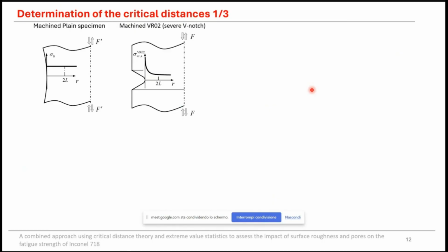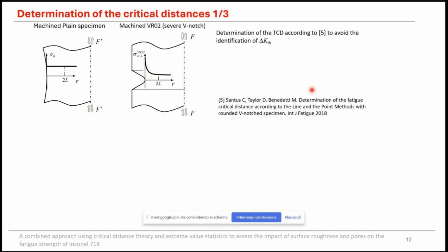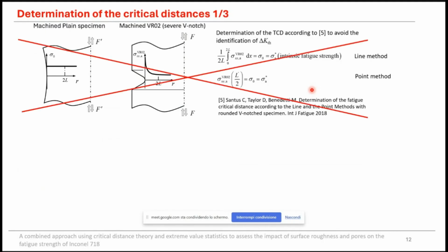In principle, we wanted to use a combination between the plain machined specimen and the severe V-notch machined specimen, following the approach proposed by Santus, Taylor, and Benedetti to avoid the identification of the threshold stress intensity factor range, which can be challenging to identify experimentally. However, this approach could not be applied, given that the pores play a key role in triggering the fatigue crack